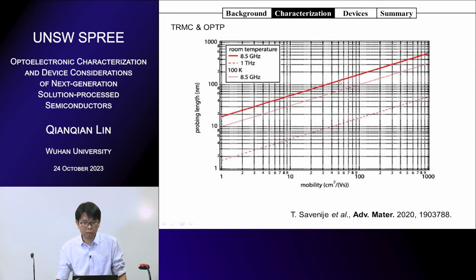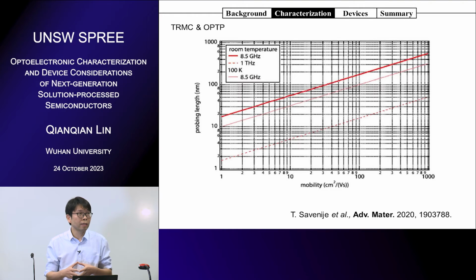So this value is around the grain scale of perovskite crystals. So if we have a larger probing length, it can have the information of charge interaction with the grain boundaries. So for these two measurements, OPTP or terahertz spectroscopy normally gives you a higher number, and the TRMC could consider the boundaries and can get more information, or get a lower mobility because of the boundaries.